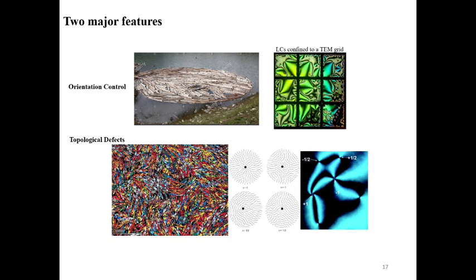It's similar in the liquid crystal system. For all those uniform color areas, you can imagine all the liquid crystal molecules are oriented the same way. So whenever they interact with another domain which is oriented differently, defects are generated here. In terms of how those defects form, we name them +1, -1, +half, -half defects.